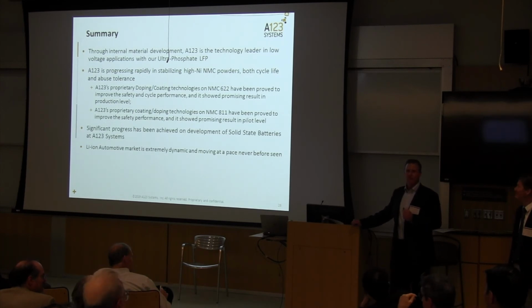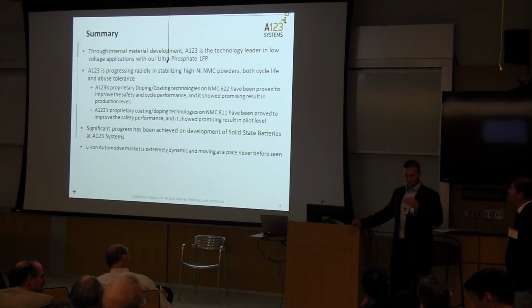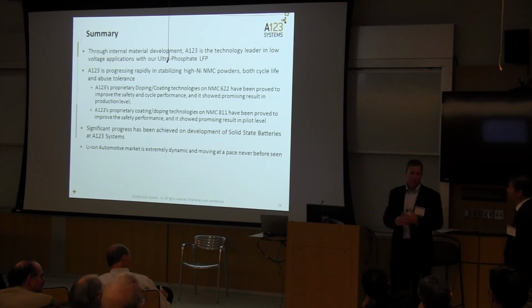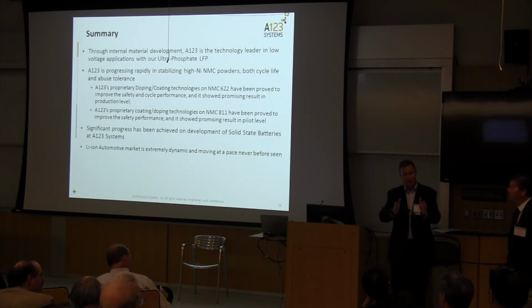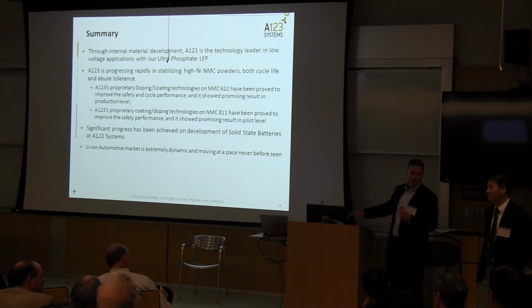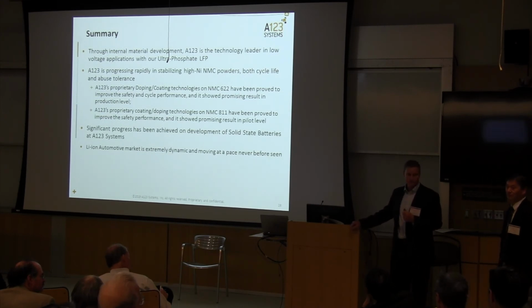No, it's an important one, because in this particular case, what we've been able to do is a process that mitigates the contact resistance in the layers, on the active material and the polymer. The polymer material is all from Ionic Materials, and they've done a great job. We don't have the internal expertise for that. So everything that we've shown had the ionic conductor and the polymer from Ionic Materials.